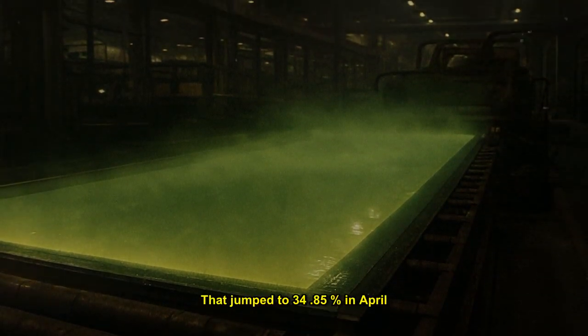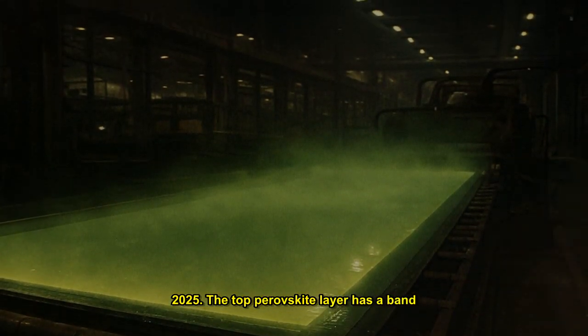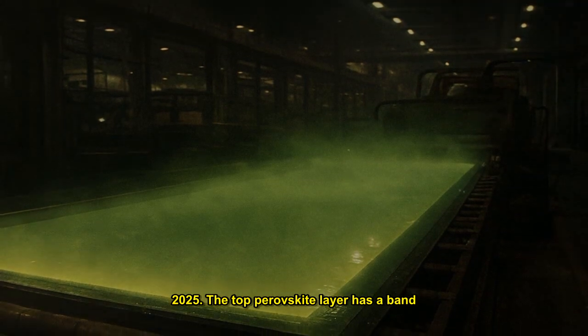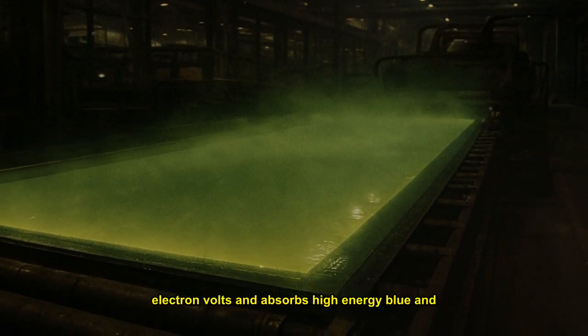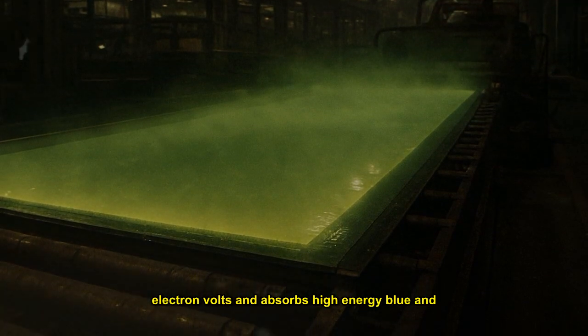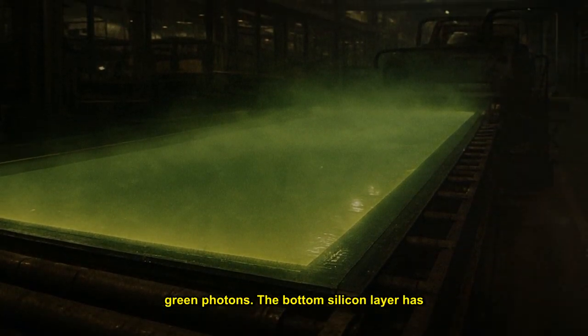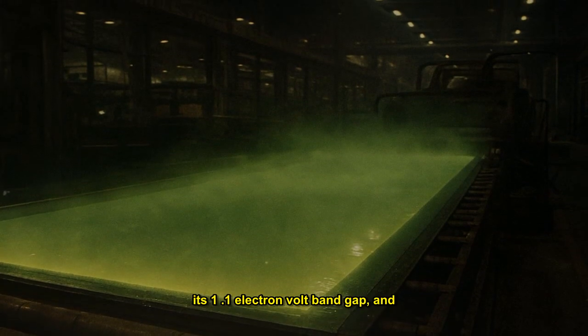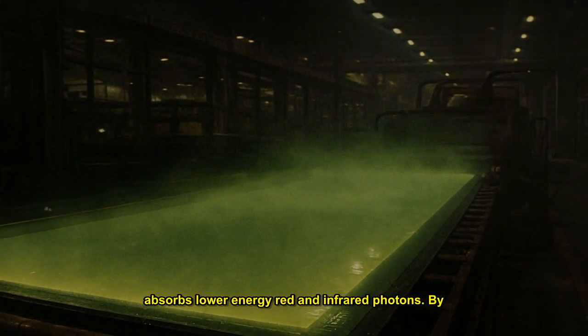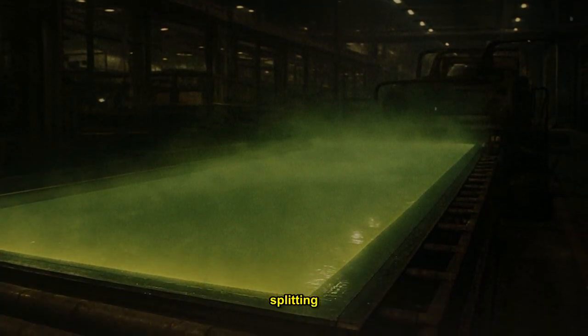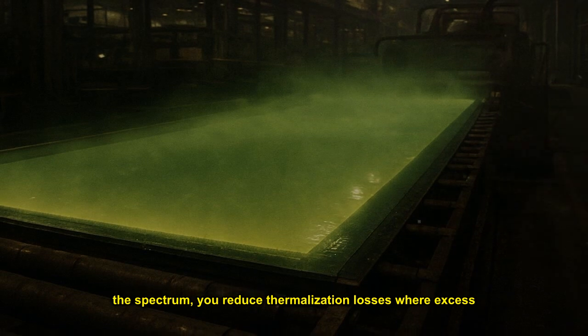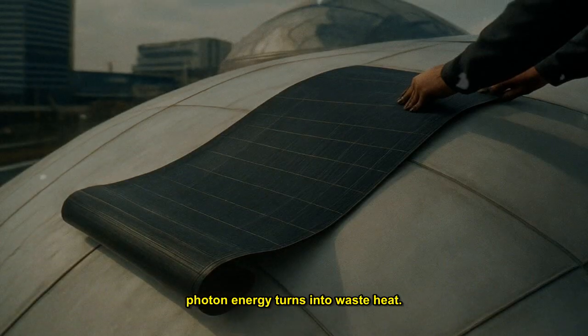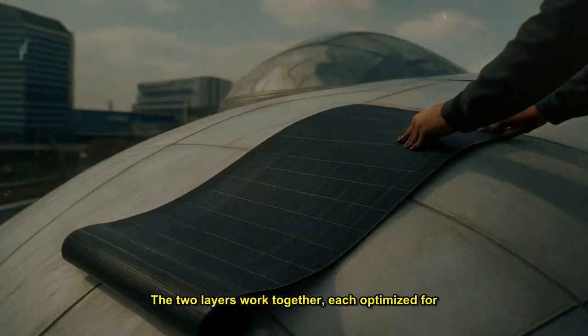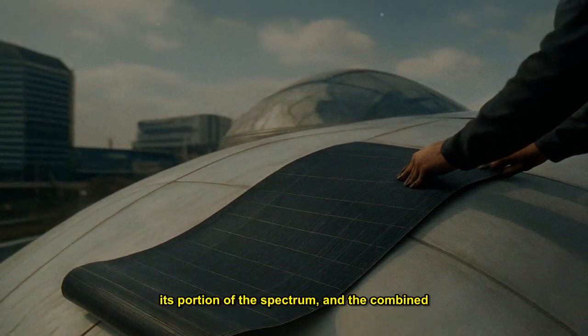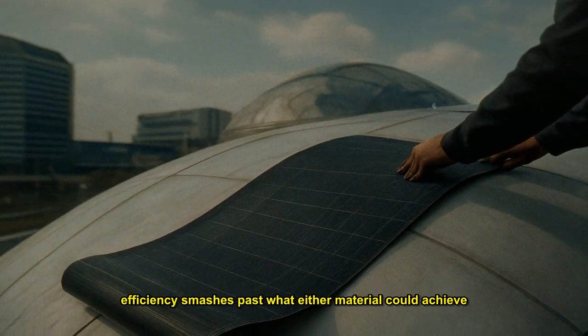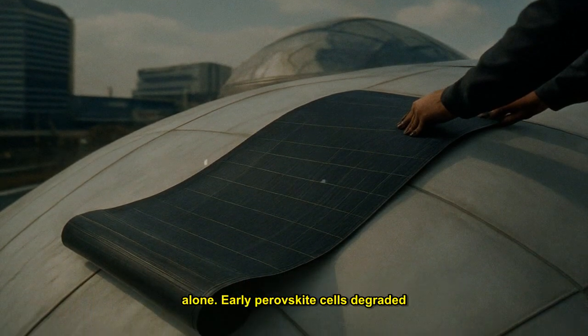That jumped to 34.85% in April 2025. The top perovskite layer has a band gap around 1.7 electron volts and absorbs high energy blue and green photons. The bottom silicon layer has its 1.1 electron volt band gap and absorbs lower energy red and infrared photons. By splitting the spectrum, you reduce thermalization losses where excess photon energy turns into waste heat. The two layers work together, each optimized for its portion of the spectrum, and the combined efficiency smashes past what either material could achieve alone.